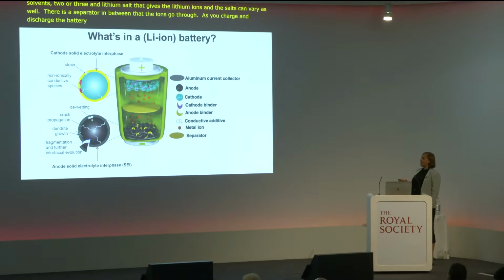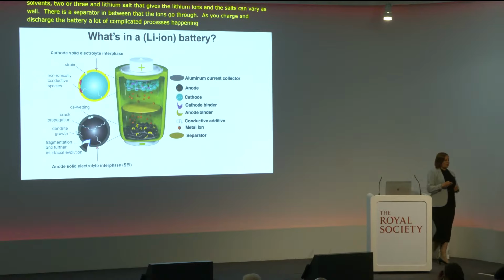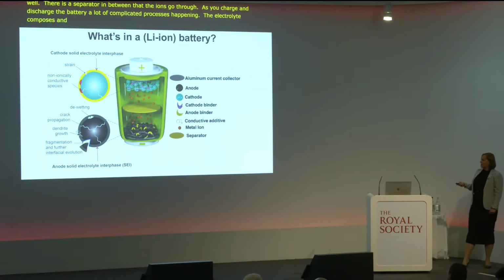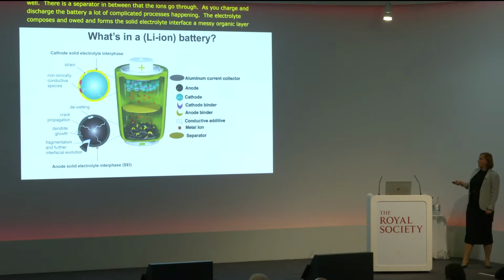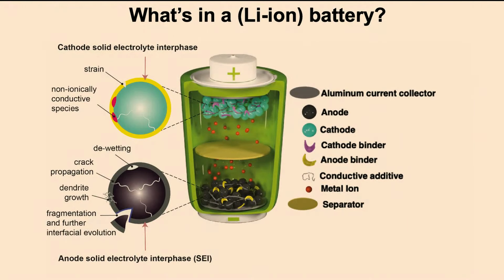Your electrolyte, for example, decomposes on your anode, and it forms the so-called solid electrolyte interface, which is a messy organic layer. Lithium can plate on top of other dead lithium that is left here on the anode and form these lithium dendrites. That's the reason why batteries sometimes explode, because the dendrites go through and pass through the separator. And also, the cathode can decompose as you have high voltages, and then you carry what's on the cathode to the anode, which contributes to the interface formation, and it's in general complicated. That's why your batteries don't last very long. That's why sometimes they explode, and that's why they're still very unreliable. So our duty here is to make them better.